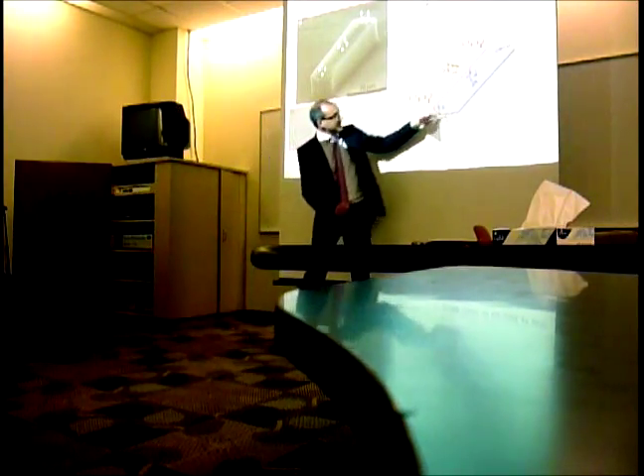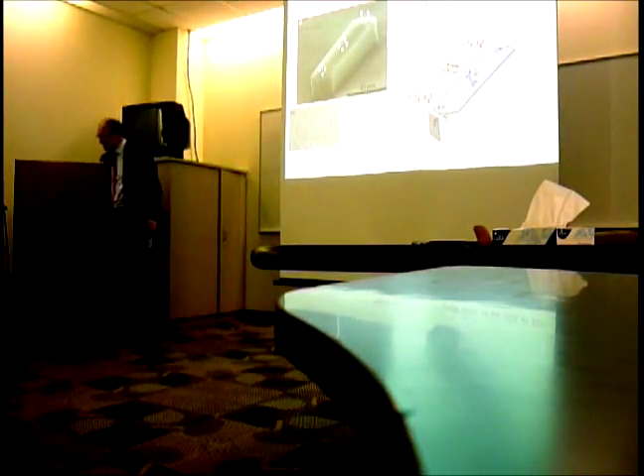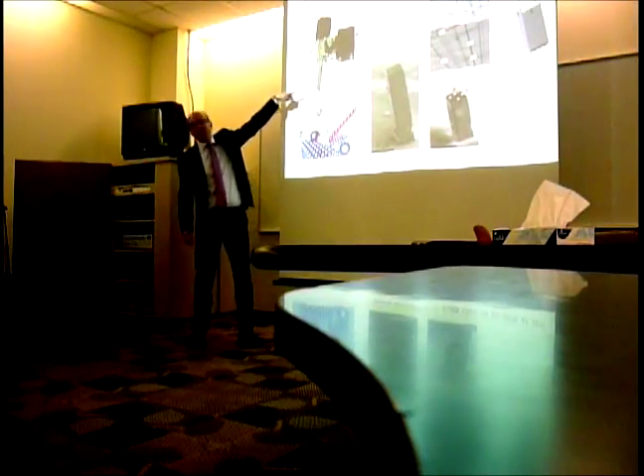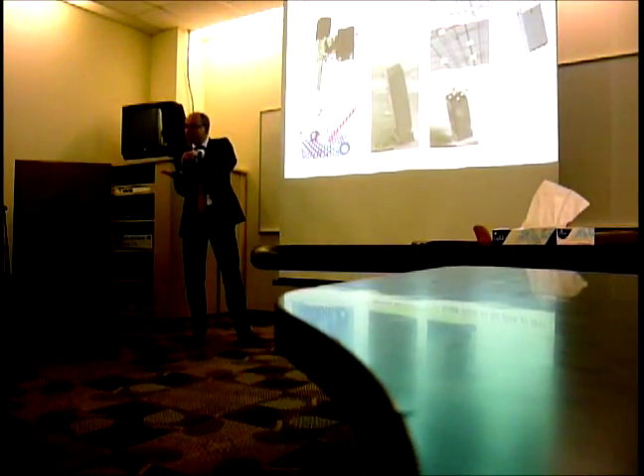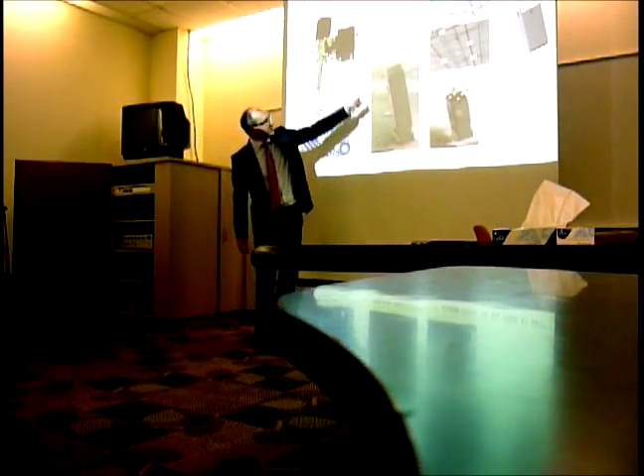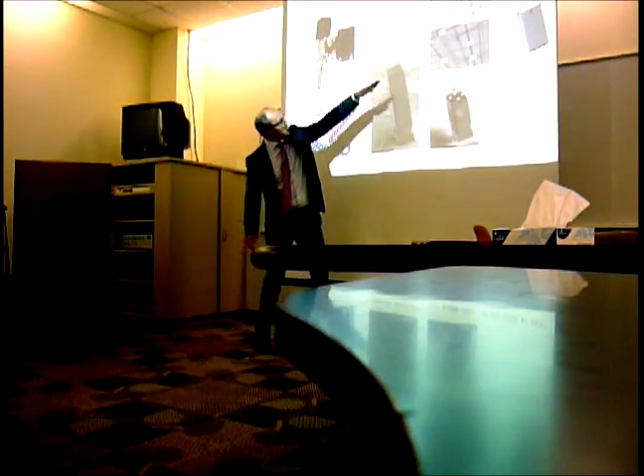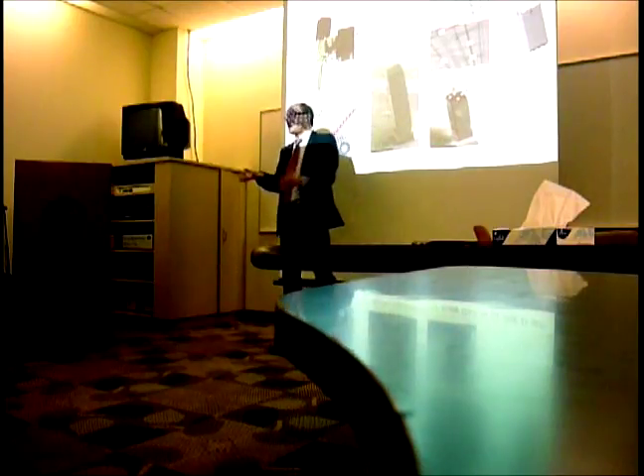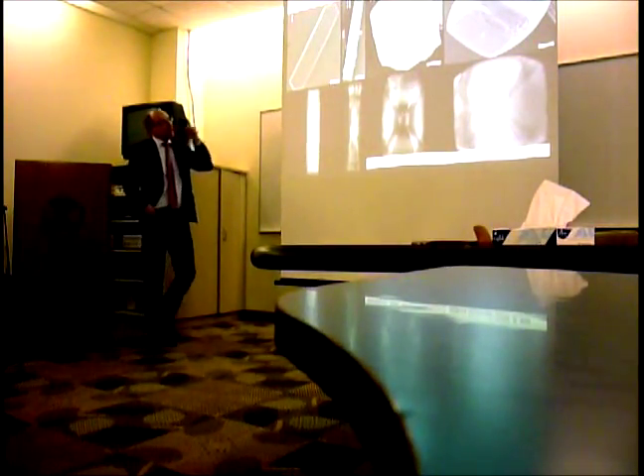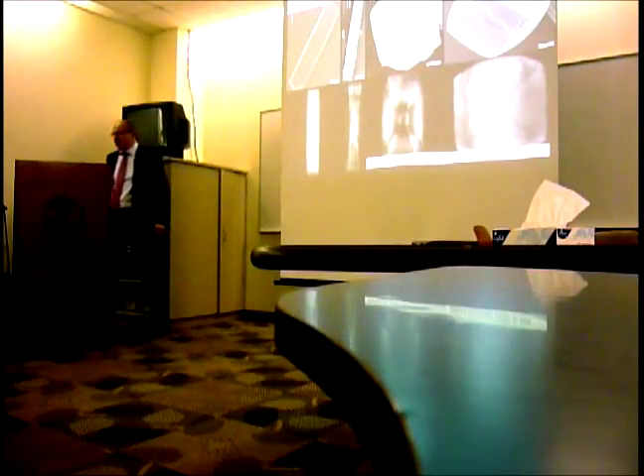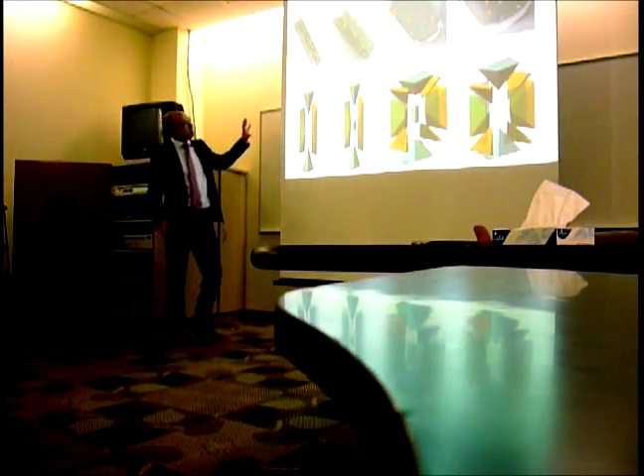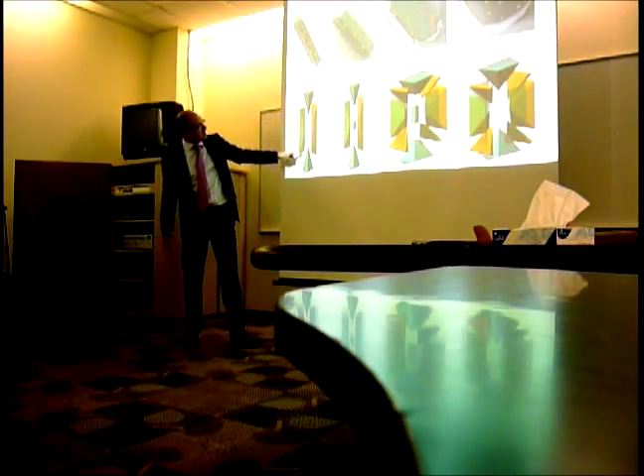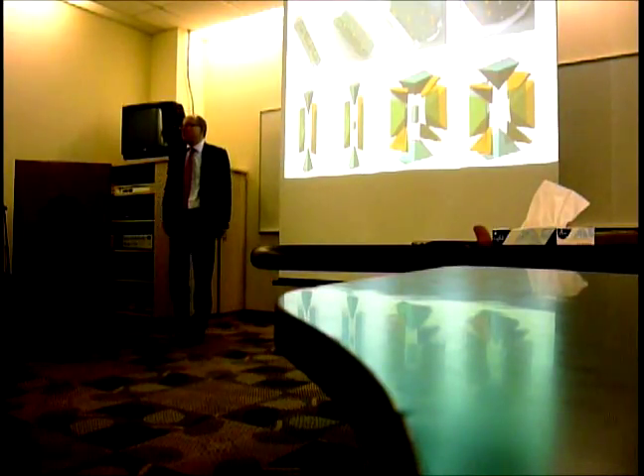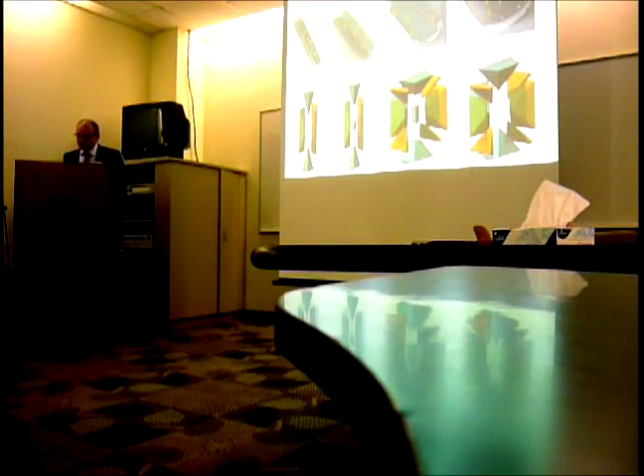And now someone can argue, I would ask it if I would be you, Bert, that's fine, but you only analyze the surface. So what is happening inside? So for this we can use what we call gallium ion beam milling. So what you do is you sputter your surface and you start to go inside the material. We take a crystal, it's almost like a skyscraper, you cut it off, and you analyze again the diffraction pattern, and then you can again prove that it is indeed the case. So this we apply to all these crystals. And here I show you the four main structures. And this led to this kind of approach, where we have, for different crystals, different intergrowth structures. So this is the classical model and solves the dispute in literature on how the intergrowth is.